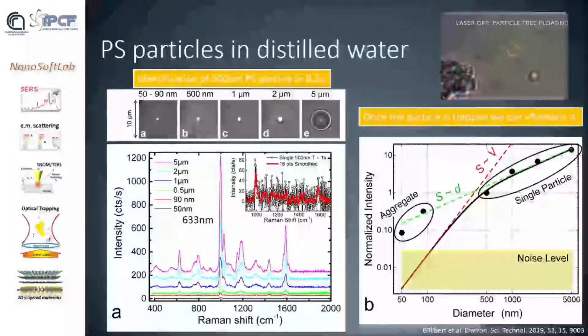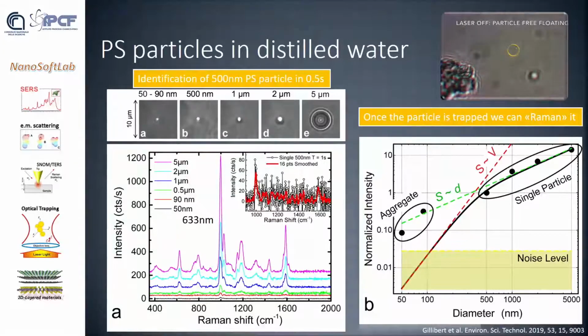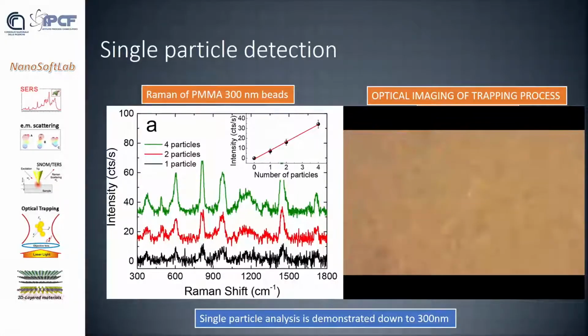Based on some model, we can understand if the particle is a single particle or an aggregate. Let's focus a bit on single particles. Here, for example, we have PMMA particles, 300 nanometers, and we can distinguish from the Raman spectrum if we have 1, 2, or 4 particles. The signal is proportional to the number of particles. You see the red line here that fits the experimental data.